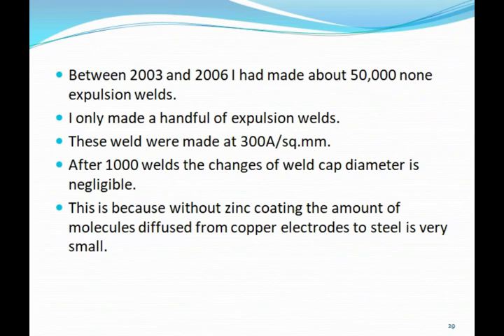These welds were made at 300 amperes per square millimeter. After 1000 welds the change of weld cap diameter is negligible. This is because without zinc coating the amount of molecules diffused from copper electrodes to steel is very small.